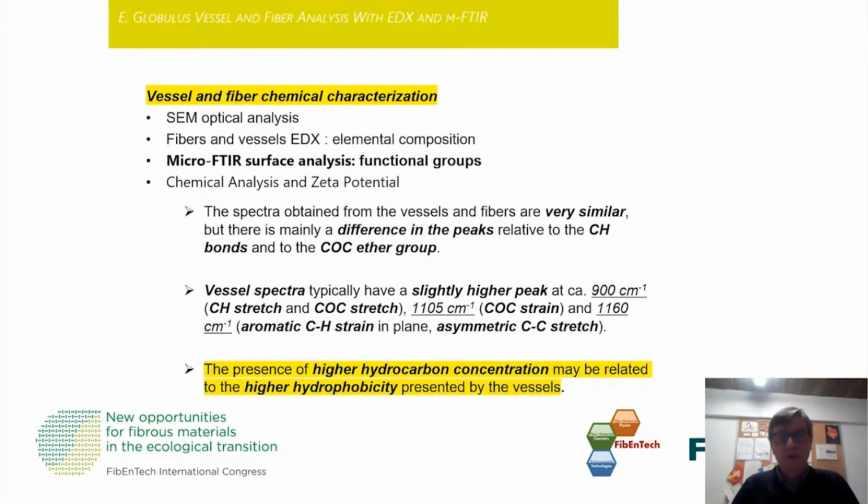The main results, which were compiled by Professor Ana Marques, are that the spectra obtained from vessels and fibers are very similar, but there is mainly a difference in the peaks relative to CH bonds and to the C-O-C ether group.